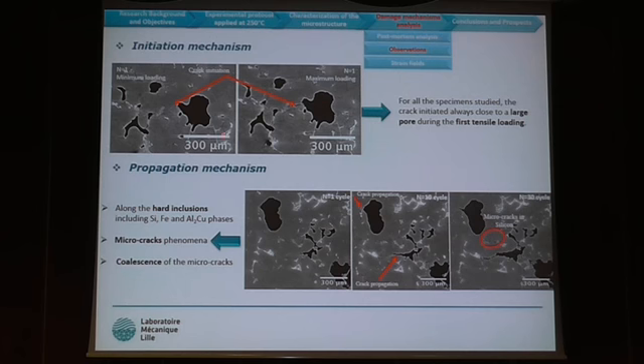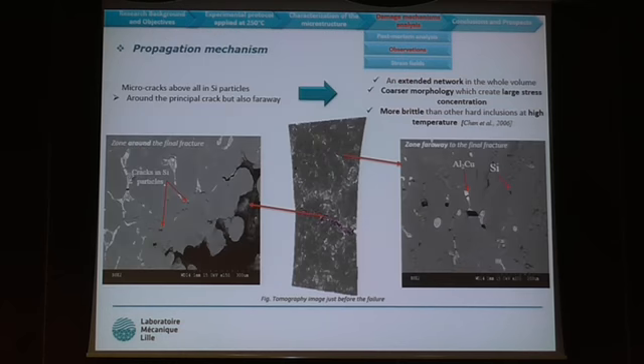So this is tomography images at the minimum loading and at the maximum loading of the first tensile loading. Here you see that at the maximum loading, the crack initiates close to the pore, and we notice that for all specimens, the crack initiates always close to a large pore, and always during the first tensile loading. Once the crack initiates at the pore, it propagates in the hard inclusions: silicon, iron, and aluminium copper phases. But you see another phenomenon, which is microcracks in the phases. So we have a lot of microcracks, and all these microcracks will later connect to create one big porosity, which leads to the final failure.